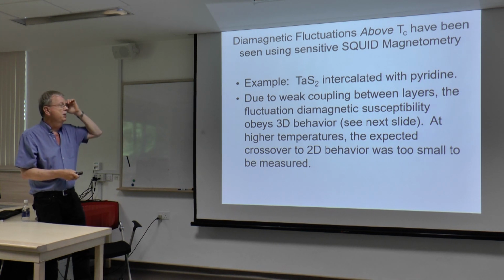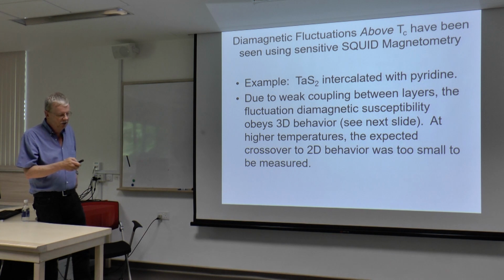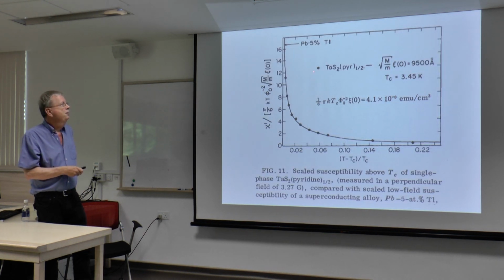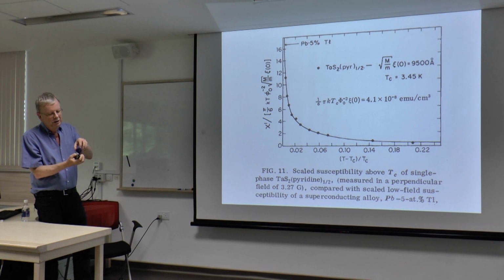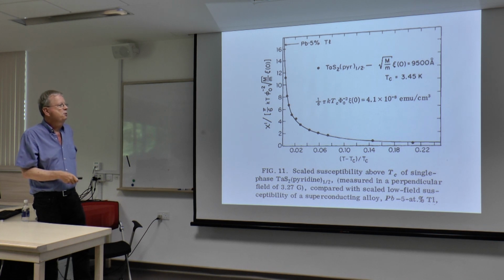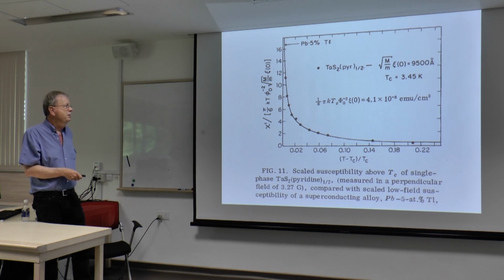And this was in the early 70s. And what they disappointingly found out was it sort of matched the data for a bulk 3D material. And so it turns out, due to weak coupling between the tantalum sulfide superconducting layers, it actually showed 3D fluctuations up to some crossover temperature, but their data wasn't accurate enough to get good data up there. So all they could talk about was 3D fluctuation. So it wasn't terribly exciting. This was still a tour de force.